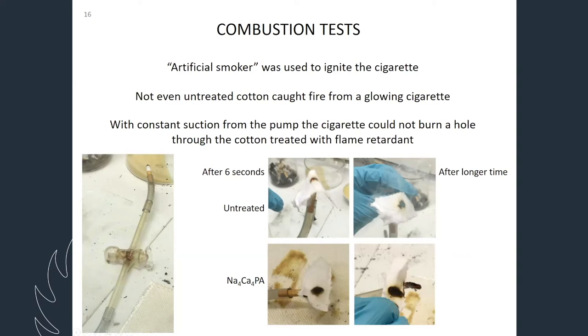So when we take untreated cotton, you can see the cigarette, the red part, makes a hole within a few seconds, but it did not catch fire. And after a longer period, it created a hole in the cloth. When it was the sodium salt or other salt, or rather to say treated sample, it chars, but it did not make a hole. And even in the right bottom, even after a long period, it did really not make a hole. You can see the cigarette is glowing quite big because I put the suction quite high, but the cloth was without a hole inside.